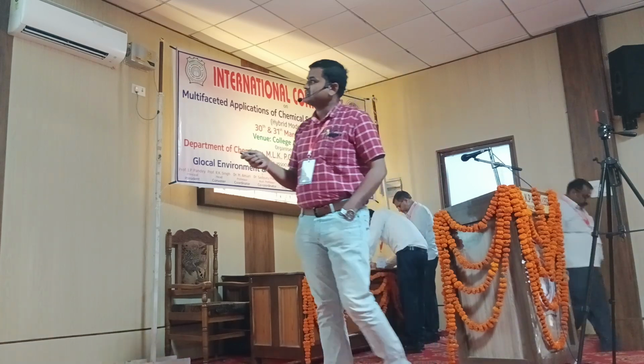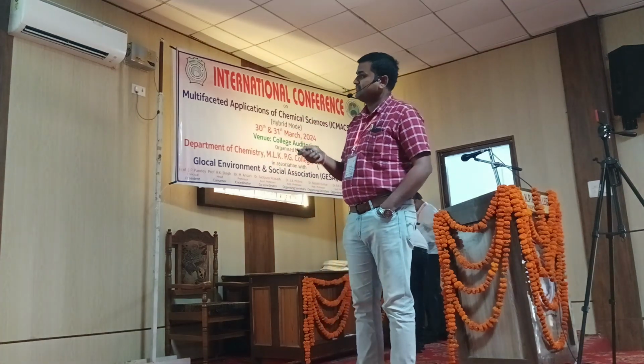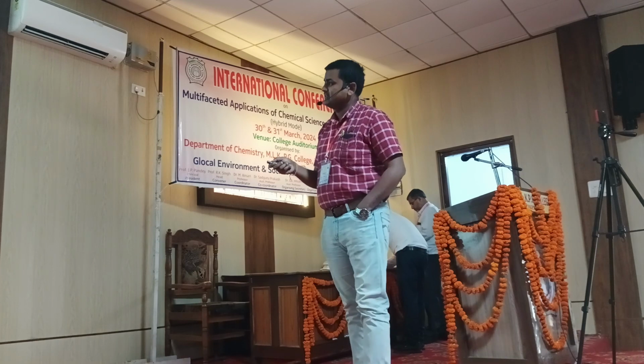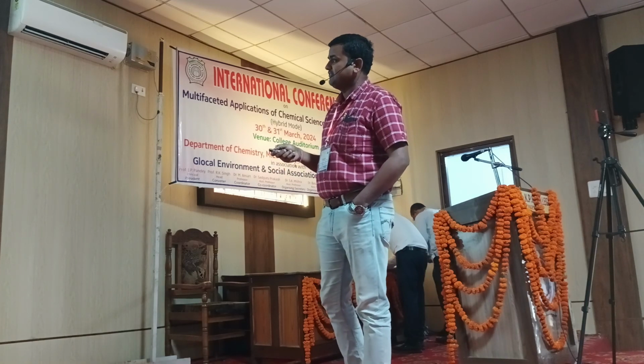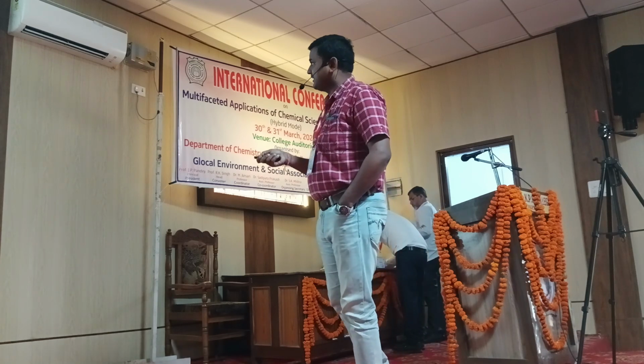We have calculated the size and morphology of the prepared graphene quantum dots, and we have found that these graphene quantum dots are just 8 nanometers in size and have a graphitic nature, which from HRTEM we can see from the lattice spacing. We have found 0.35 nanometer, and their graphitic nature was also confirmed by XRD and Raman.